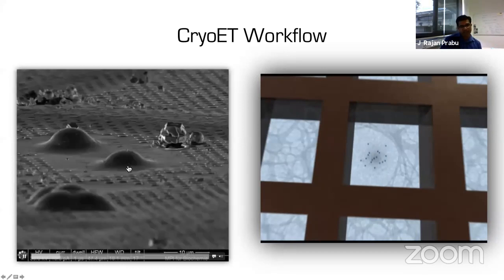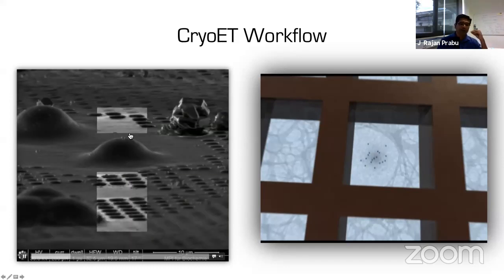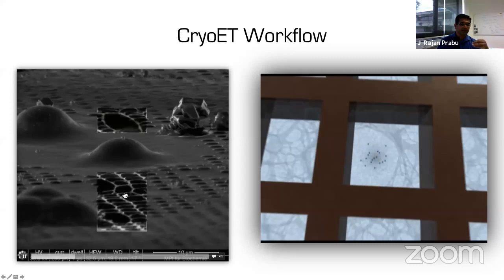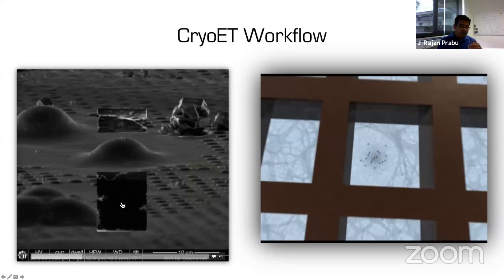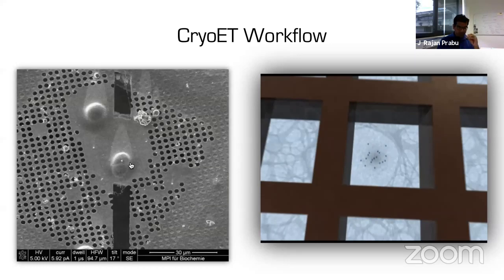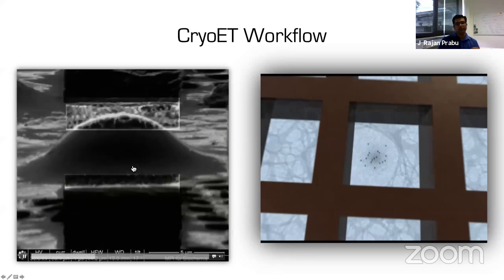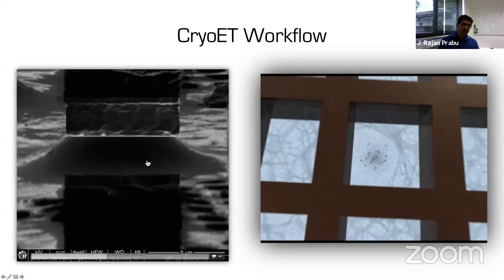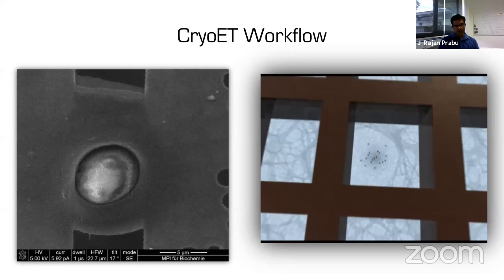Then you put a mark because you really have to go slow. You don't want to burn the cells away. Then you pass the gallium ions. You completely burn away what's on the top and what's on the bottom. Then you have to go slower and slower until you reach the point of interest, and the correct thickness. Because if it is too thick, the microscope will not get enough transmission. It's going to absorb all the data, so you will not get any good information out.